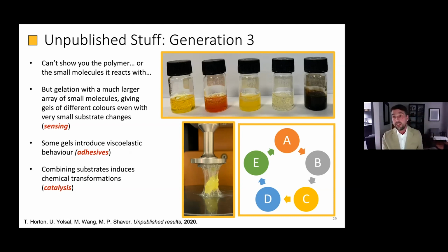So the three application areas that we're looking at is sensing, so we want to be able to sense different substrates. The substrates that are used in the vials that you see at the top here differ by as little as a single carbon, and you can see the dramatic changes both in gel strength and color that we're observing in these systems. We also have other substrates that are introducing viscoelastic behavior and work as triggerable adhesives, so there's no adhesive behavior until you have that switch, and then a single molecule introduces that adhesive performance.